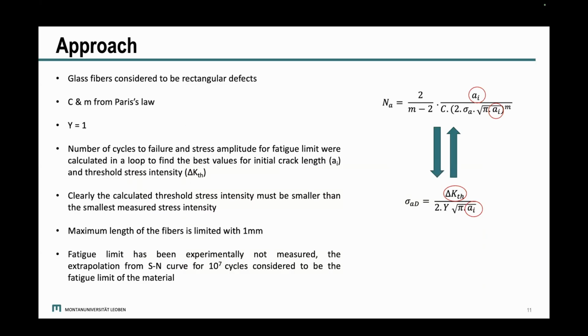We also developed a MATLAB code to find the optimum parameters for the calculations, better to say, to minimize the difference between the calculated SN curve and the measured SN curve. The parameters which could be optimized in the calculations are the initial crack length and the threshold stress intensity. We know that for short fiber reinforced polymers, on the one side, the fibers could enhance the mechanical properties of the material, but on the other side, each fiber could be a possible spot for a defect in the material. And also the initial crack length should be maximum at the length of the fibers. Literally, the maximum length of the fibers is 1 millimeter, but we know that during the production process, the fibers will break, and finally the length of the fibers is in most cases smaller than 1 millimeter.